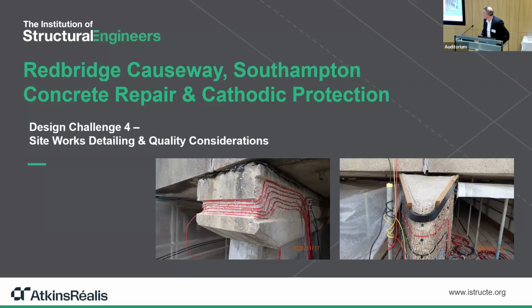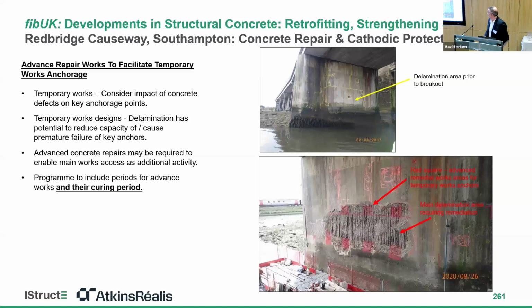Over to Steve. Afternoon, everybody. Just going to look at a couple of slide details. This particular slide shows Pier 8, which is a pier that had a particularly large delamination on the base. You can see the yellow arrow pointing to it there. This presented a problem in health and safety, in that there was potentially a large amount of concrete that could fall, and plus it needed to be removed so we could attach the scaffold anchor plates, which is what's shown in the red squares on the bottom picture.